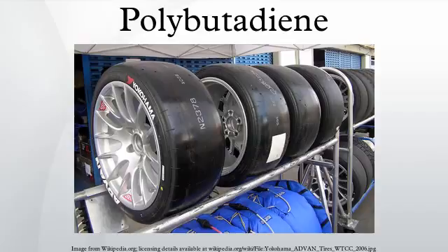Plastics. About 25% of the produced polybutadiene is used to improve the mechanical properties of plastics, in particular of high-impact polystyrene and to a lesser extent acrylonitrile butadiene styrene. The addition of between 4 and 12% polybutadiene to polystyrene transforms it from a fragile and delicate material to a ductile and resistant one. The quality of the process is more important in the use in plastics than in tires, especially when it comes to color and content of gels, which have to be as low as possible. In addition, the products need to meet a list of health requirements due to its use in the food industry.